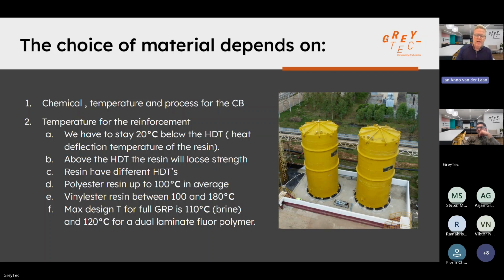So typical maximum design temperatures for composite products, piping and tanks are 110 degrees C for full FRP in combination, for example, with brine, and 120 degrees C for special dual laminate constructions. For even higher temperatures combined with highly corrosive liquids, PTFE or PFA lined steel can be a suitable alternative. To give you a better idea of the production process, we will now show a short Polyplast video.